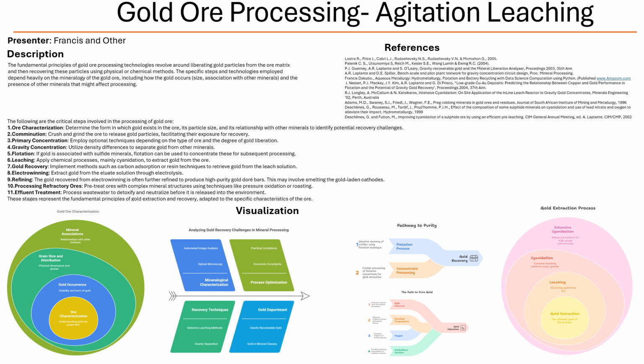And the notes provide a really good overview of the key factors that influence the efficiency of cyanidation. Like what? Well, they talk about things like the surface area of the gold particles. Smaller particles dissolve faster. That makes sense. More surface area, more contact with the cyanide. Exactly. And they talk about the concentration of cyanide, the concentration of oxygen, the temperature, the pH, the presence of other ions. Wow, there's a lot to consider.